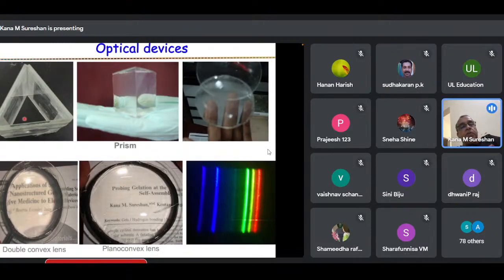First, we wanted to see whether we can use it for optical applications. So we made a prism out of this just by pouring a hot liquid of this gelatin in oil. After some time, when it cools down to room temperature, it becomes a nice jelly prism. And of course, you can see the pattern produced using that prism. Also, if you put this in a watch glass, after some time it will become a plano-convex lens. If you put two plano-convex lenses face to face, you get a double convex lens. Of course, you can see my hand magnified here by looking through that lens.